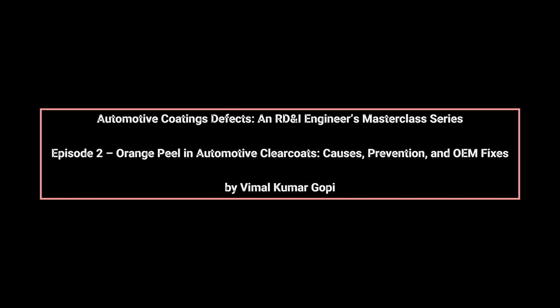The flash-off period, the time allowed for solvents to evaporate before entering a bake or oven, is a key lever. Moving the panel into the oven too quickly forces rapid surface skinning before internal flow can smooth the film. Conversely, extending flash-off inappropriately can reduce production throughput, so careful adherence to technical datasheet (TDS) recommendations and seasonal adjustments for temperature and humidity are necessary.